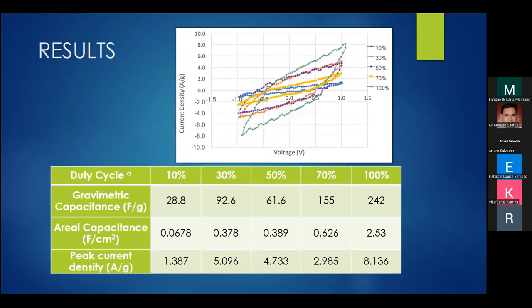And then for the cyclic voltammetry characterization, we present here the consolidated CV plots of the five films grown at 10, 30, 50, 70, and 100% duty cycle. So they are quasi-rectangular. Of course, ideally you want it to be rectangular, but this is an electrochemical system, so you expect it to be quasi-rectangular. So in calculating the capacitance, we just took a voltage window